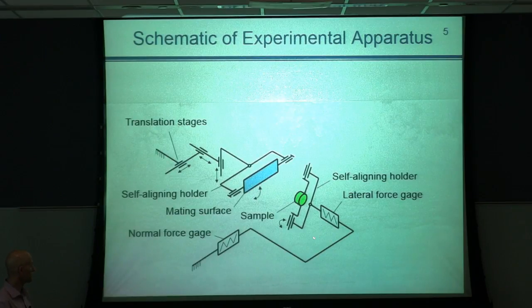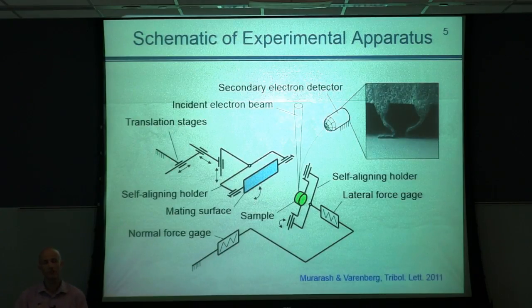normal and tangential forces. So when the mating surface is brought in contact with the patterned sample, a normal force gauge is loaded, and we can control the normal load. When the sample is dragged in parallel to the contact plane, we can measure friction forces by analyzing deflection of this sensor. This device is built to be very small, and it can be fit into the vacuum chamber of